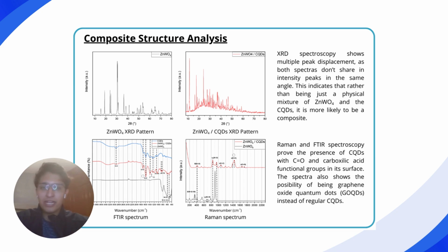About the chemical composition of the carbon quantum dots, we can see in both the FTIR and the Raman spectroscopy many carbon and oxygen bonds, having a strong presence of carbonyl groups in both, possibly from acid groups that we can see in the FTIR spectra. We can also see many carbon double bond peaks, mainly in the aromatic region. In the FTIR spectra, we can see a narrow proliferation of carbon and hydrogen, indicating the possibility of the presence of graphene in the carbon quantum dots. In sum, with the presence of acid and carbonyl groups, we could reasonably assume the presence of not only carbon quantum dots, but maybe also graphene oxide quantum dots. However, further testing is needed to confirm this theory.